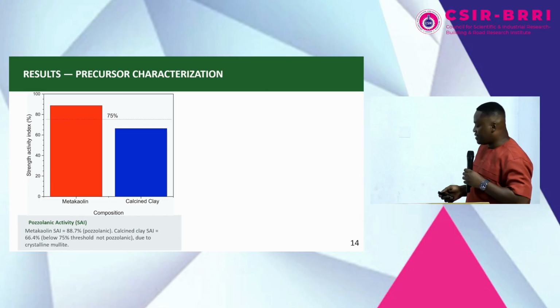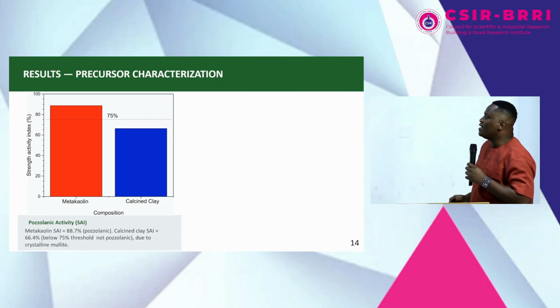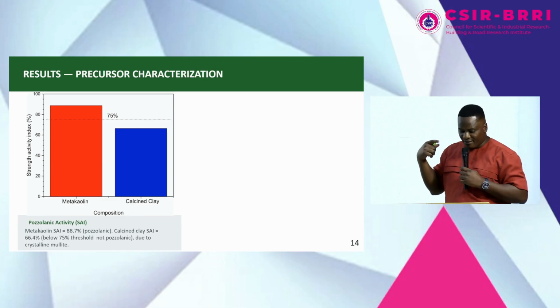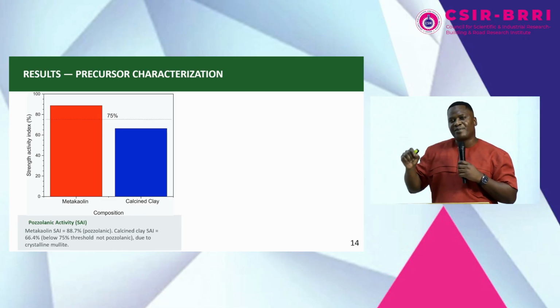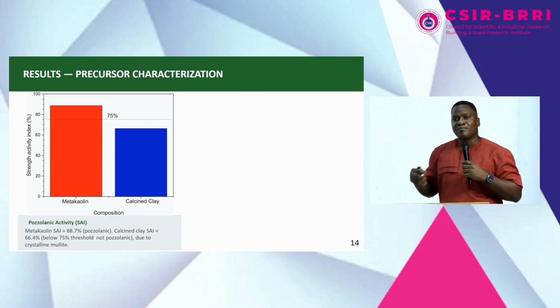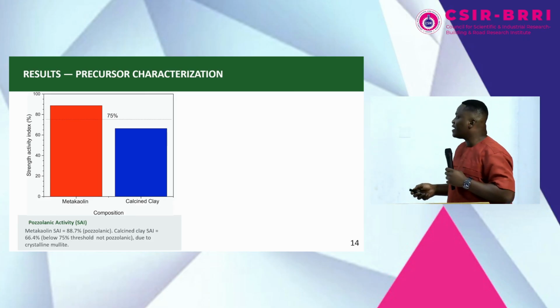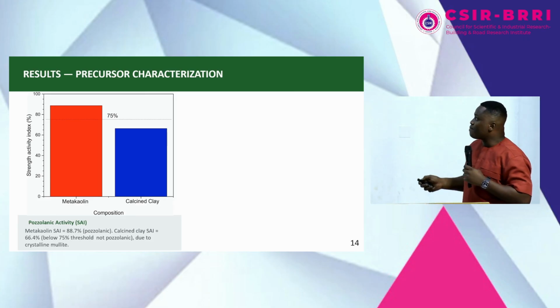All right, so these are the strength results of the two materials. Now remember, we are trying to replace metakaolin with calcined clay, so the emphasis here is on the calcined clay. You realize that the strength of the metakaolin is obviously higher than the calcined clay. From the introduction, I mentioned that metakaolin is a better version of calcined clay because of the peculiar minerals it contains. So it's not surprising that the strength is far better.